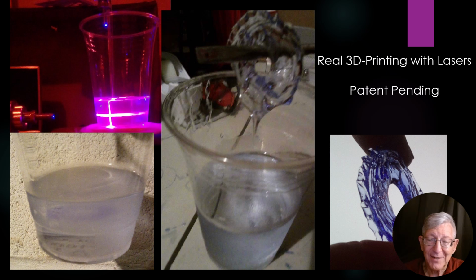Let me try to center myself in the cameo box over here. On the left extreme side, at the top you see a picture of the setup we use. You have two lasers, one at the top. You see the little blue dots. The one at the top is the vertical laser, and the one on the left is the horizontal laser. And those two lasers were coordinated such that they intersected within a pool of liquid resin. And this whole process took a few seconds. It was much less than a minute, probably 10 seconds or less.